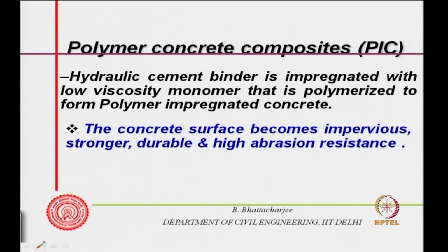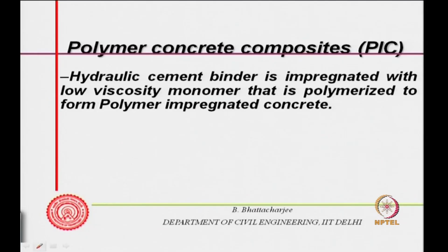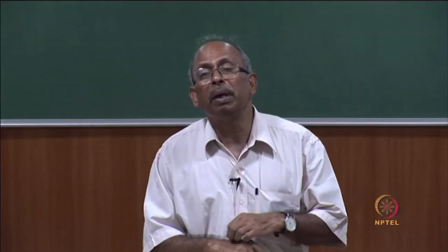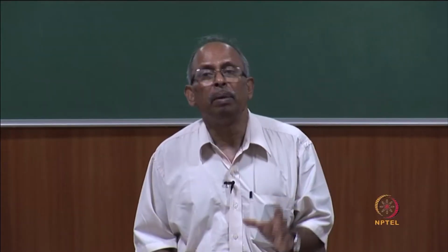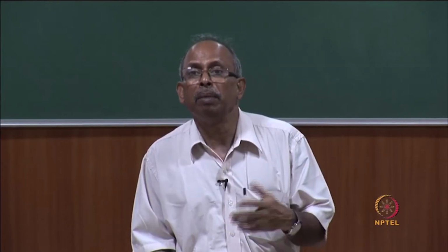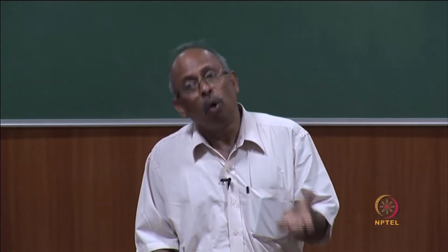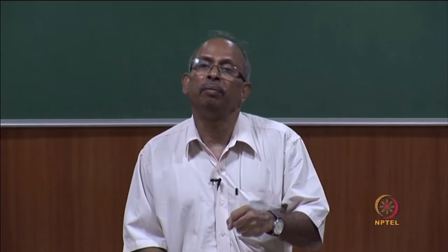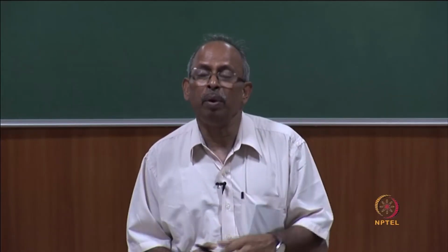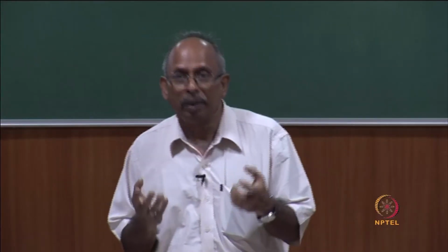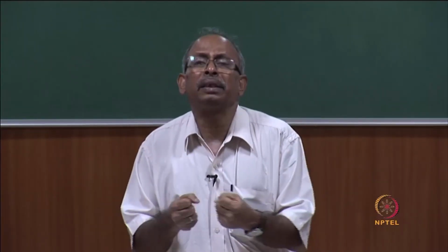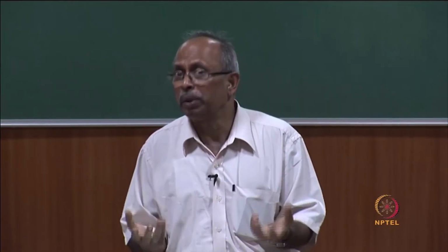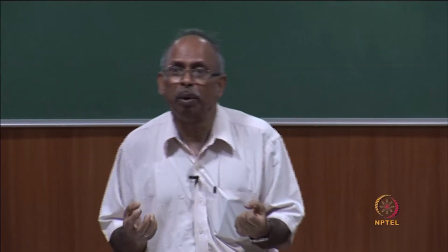Originally you must have a good concrete, and a low viscosity monomer is pre-impregnated into the concrete and then polymerized to form polymer impregnated concrete. Now, this polymerization can occur because of radiation, but that is a health hazard. It can be done by thermal techniques, thermal polymerization, radiation polymerization, or by chemical polymerization with a kind of hardener system, like, if you are familiar with it, araldite, which is of course an epoxy. There are various kinds of glues, two-component glues, and epoxy is one material which is very popular.